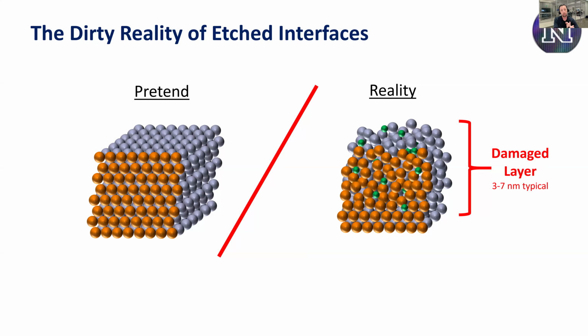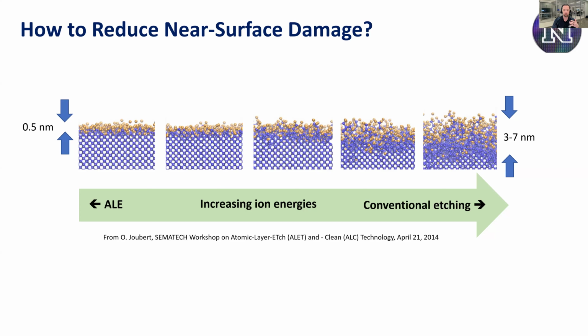That's where atomic layer etch comes in. So the interesting thing about atomic layer etch to me is this decreased subsurface damage. This damage layer could be reduced. Yes, there are other potential advantages. Maybe you want to etch 3 nanometers. I've had situations where people ask me how do I etch 3 nanometers of a thing. That's really hard to do in a timed etch. Atomic layer etch is going to work really nicely there. Cyclic, really well-controlled etch rates, awesome.